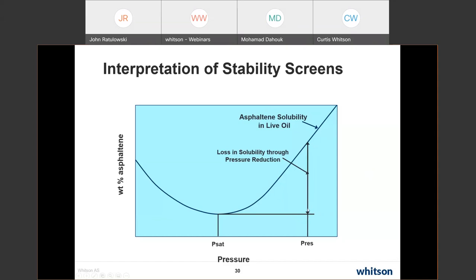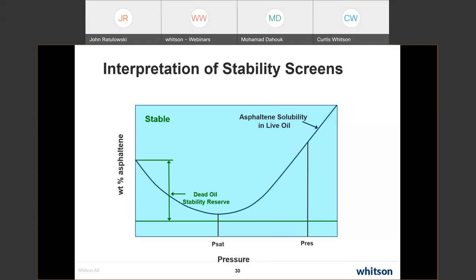So this is the PVT screen. This is what the PVT screen tells us: the potential loss in solubility through pressure reduction. Now, what about the other screens? The other screens give me a dead oil stability reserve. If I have a large dead oil stability reserve, either indicated by compositional data or by a direct titration, chances are that I have enough to take care of any loss in stability that I see as I decrease in pressure. So in this case, you can see I have enough stability reserve that I don't ever really have a problem with precipitation.